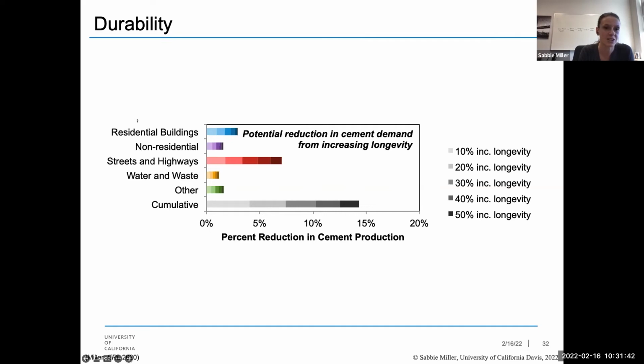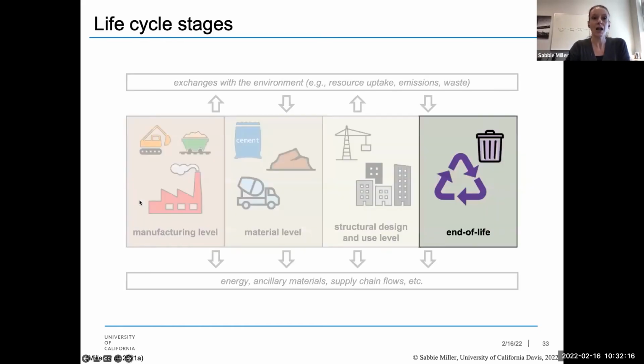What I'm showing you here is our cement consumption for different infrastructure systems and buildings, and we are increasing the longevity of those systems, assuming minimal levels of maintenance or replacement to increase that longevity. And we see that streets and highways in particular, if we're able to increase the longevity without having a large increase in maintenance and replacement, we could actually have a really significant reduction in the amount of cement necessary for those systems. So again, trying to understand how the longevity of that system will start to influence our overall materials consumption. There's also the potential to lower impacts at the end of life stage.